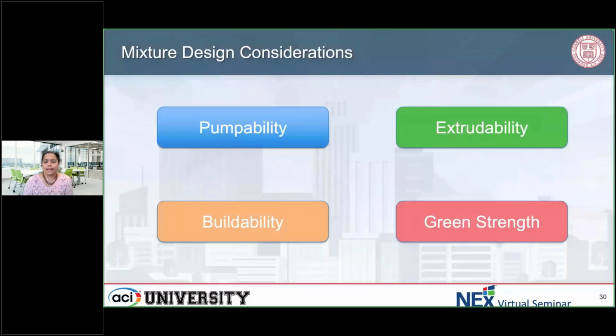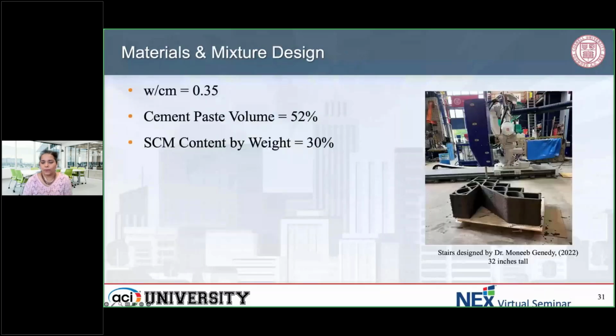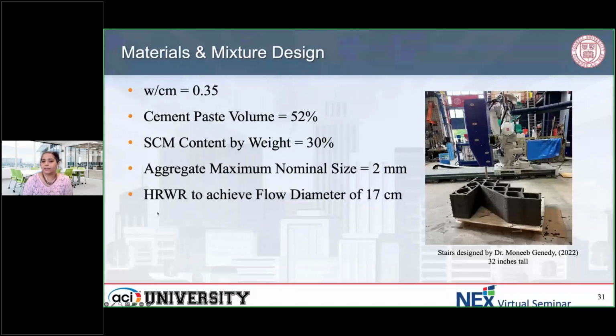So keeping all these in mind, we have a mixture that we developed in-house so that we know our water to cement ratio and what's going into our mixtures. So we have a paste volume. This is not cement paste, but just the powder paste content, which is 52%, of which we're using 30% supplementary cementitious materials right now. And our nominal aggregate size is 2 millimeters. We use a high range water reducer such that this material system is flowable. We use the flow mortar table test, that small slump cone, and then we pour the material and lift it up. So almost like an SCC, it just flows. And then you measure the diameter of that slump flow, which is about 17 centimeters in this case.